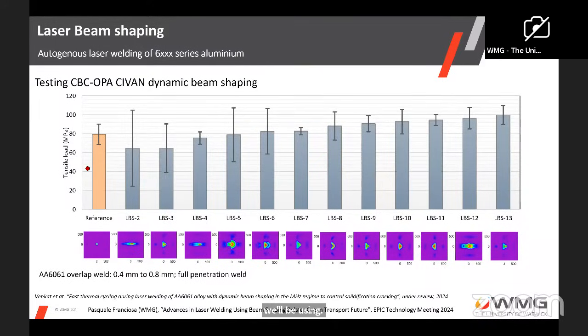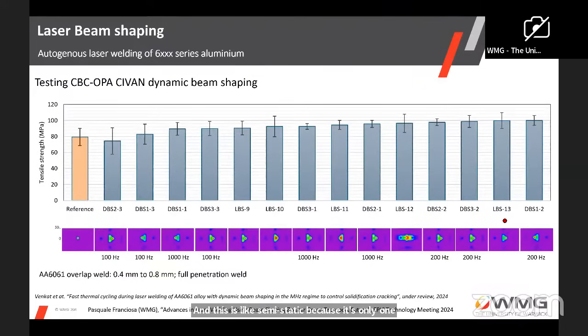So those are the tensile loads in megapascal for those shapes. Now, if you compare the baseline on the left-hand side, so close to 80 megapascal, and then you see how much improvement you can get by changing the shape. It's almost 20% improvement only by changing the beam profile. And this is semi-static because it's only one shape. Then if you add the dynamic element, in this case we didn't go more than 1000 hertz, you can see again the trend. There is a margin for improvement.